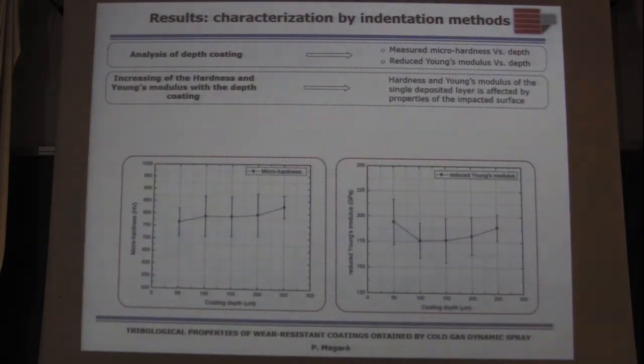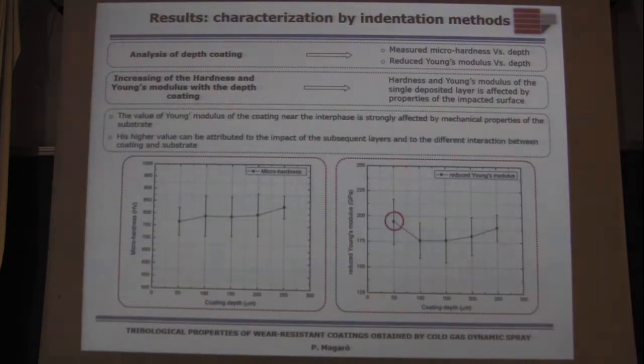And we can observe that microhardness and Young's modulus increase with the coating depth. This observation suggests how the single deposited layers are affected by the properties of the impacted surface.